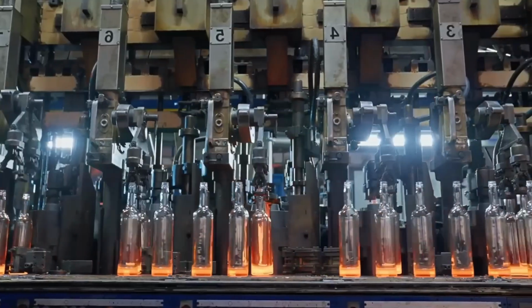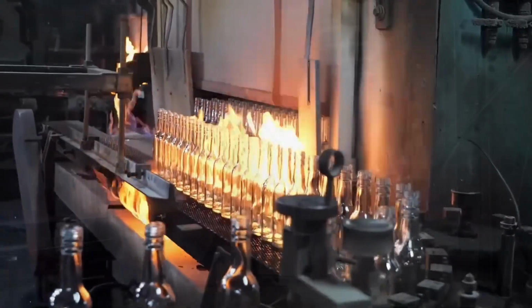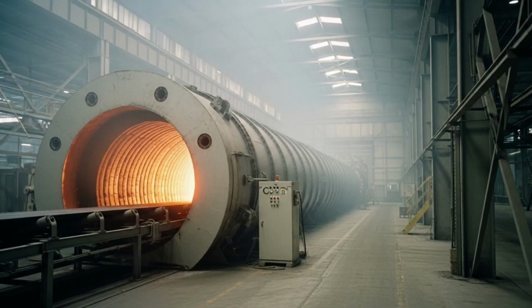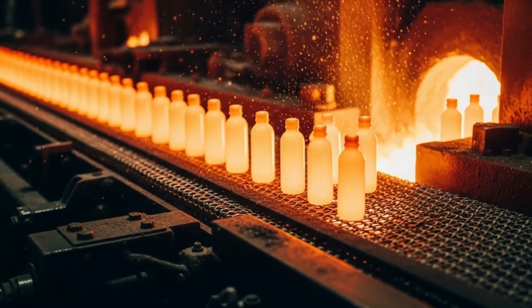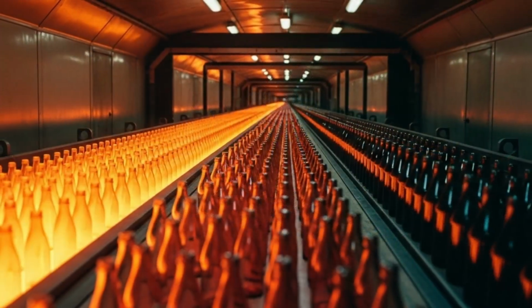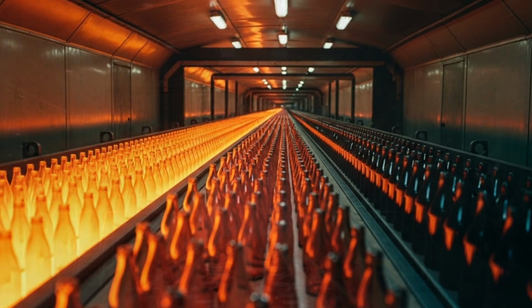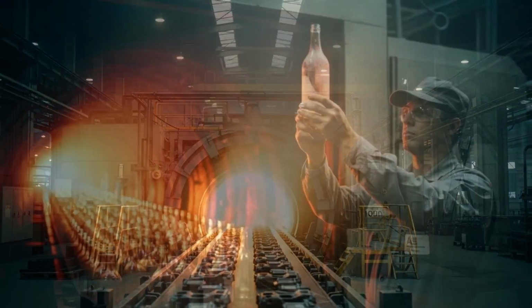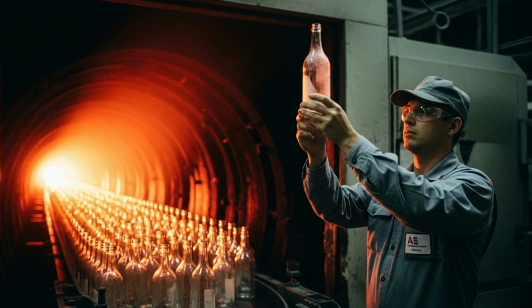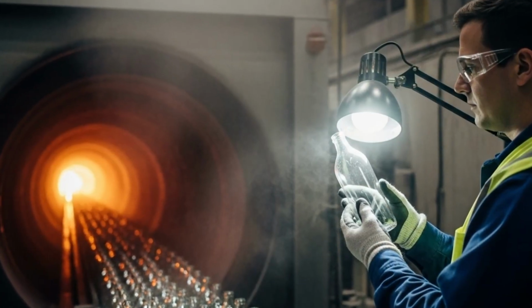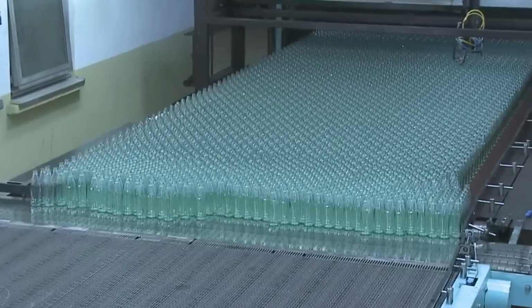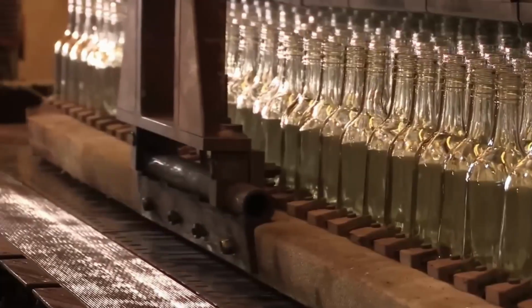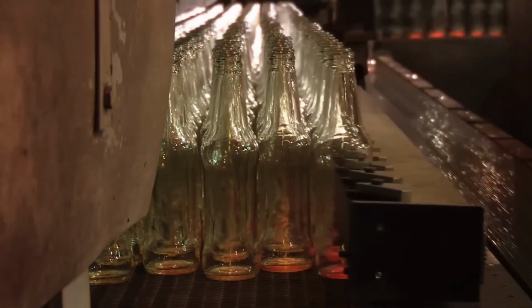This conveyor takes them to an annealing tunnel, a horizontal furnace about 50 meters long. Inside, the temperature gradually drops, from 600 degrees Celsius down to room temperature in about 30 minutes. This controlled cooling is no minor detail. It prevents the glass from building up internal stresses that could make it shatter with the slightest temperature change. Without it, a perfectly formed bottle might crack on its own hours or even days later.